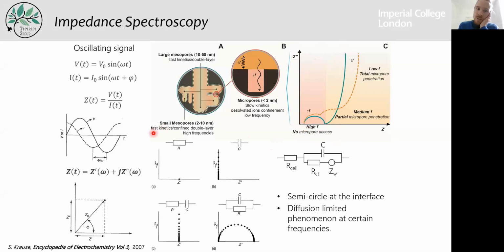And that is the Nyquist plot that corresponds to the complex impedance here on the ordinates with the real impedance on the axis. This part corresponds to the high frequency, and this part corresponds to the low frequency. It is shown that for different electrical components, such as the resistance, this Nyquist plot will be only one single point, because the impedance of the resistance is independent of the frequency. The impedance of the capacitor is dependent on the frequency, and this is why you see, as the frequency lowers, an increase of the imaginary impedance. If you put the two of them in series, then you will start observing this system, where that is the value of the resistance. And if you put the two of them in parallel, you observe this typical semicircle.